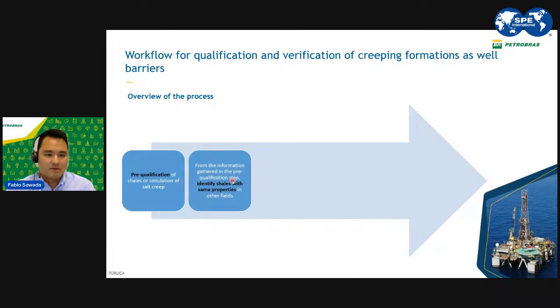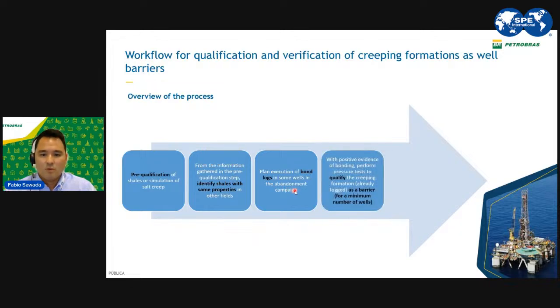So from the information gathered in the pre-qualification, in the case of shales, we could identify, as I said before, the shales with the same properties in other fields that have the same type of formation and mechanical properties. We can plan the execution of bond logs in some wells in the abandonment campaign, when we are talking about mature fields. With positive evidence of bonding, in order to qualify the formation, we should be performing both a bond log and a pressure test in the annulus, so we can be sure that the response in the bond log really is a good response for a barrier.